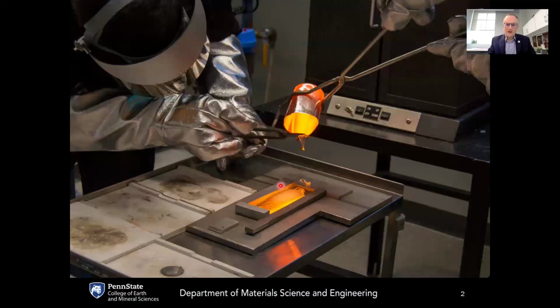Here's a picture of some of my students pouring out some freshly melted glass from one of the furnaces in our lab. You can see as the molten glass comes out of the crucible, it is flowing like a liquid. But as the glass forms at the bottom here, the viscosity is increasing rapidly, and this molten state is gradually converting into the glassy state. So it's gradually going from something that appears very much like a liquid to something that appears more like a solid. When this happens, this is called the glass transition.